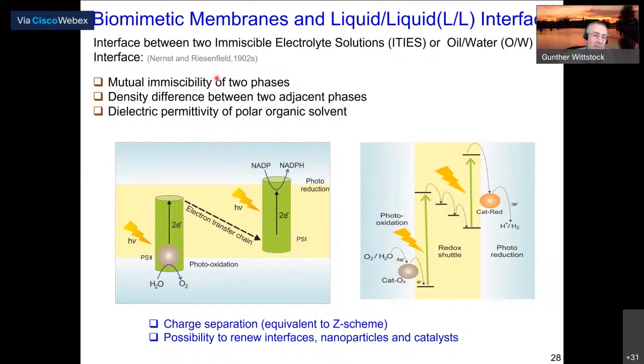So if we look at working systems that do photoconversion in nature, we find that these are usually biological membranes, and a technical system which could mimic that is either biomimetic membranes or liquid-liquid interfaces. Such liquid-liquid interfaces can be formed between two immiscible electrolyte solutions, like an oil-water interface. The requirements are that the two solvents are not miscible, there should be a density difference between the two liquids so that they form a stratified layer, and both should have a dielectric permittivity. In particular, that's an issue for the organic solvent.